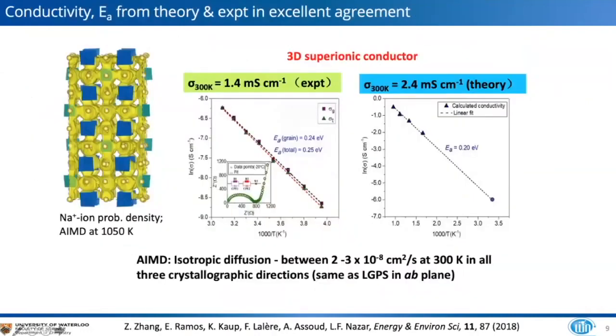So we carried out AIMD, ab initio molecular dynamics studies to understand sodium transport in this material. And you can see this is the sodium ion probability density. You can see that there's isotropic conduction, as shown by this probability density in all three dimensions. And you can furthermore see that the experimental conductivity of 1.4 millisiemens is in very good agreement with that predicted by the AIMD theory, which is 2.4 millisiemens. And similarly, the activation energy by theory of 0.2 electron volts is very similar to what we obtain from experiment, about 0.24 electron volts.